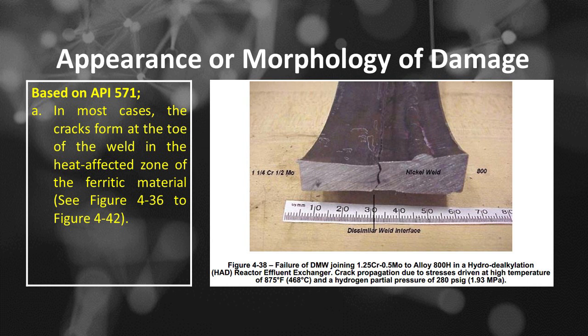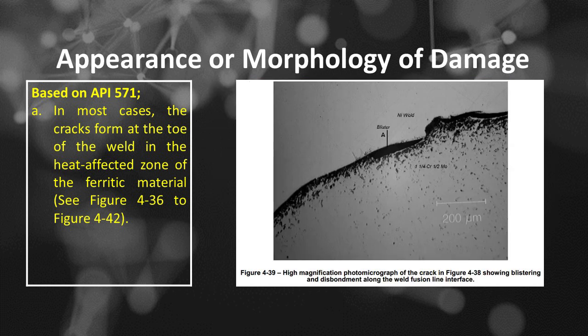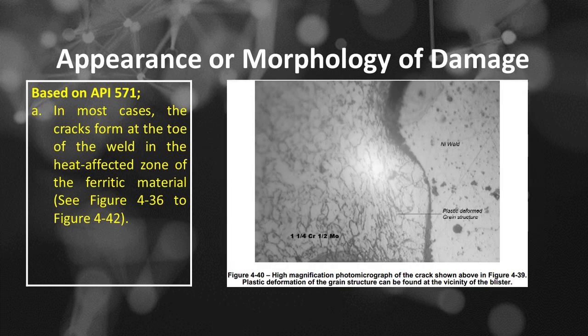See Figure 4:38, failure of DMW joining 1.25 Cr 0.5 Mo to alloy 800H in a hydrodealkylation, HDA, reactor effluent exchanger. Crack propagation due to stresses driven at a high temperature of 875 degrees Fahrenheit, or 468 degrees Celsius, and a hydrogen partial pressure of 280 psig, or 1.93 MPa. See Figure 4:39, high magnification photomicrograph of the crack in Figure 4:38 showing blistering and disbondment along the weld fusion line interface. See Figure 4:40, high magnification photomicrograph of the crack shown above in Figure 4:39. Plastic deformation of the grain structure can be found in the vicinity of the blister.